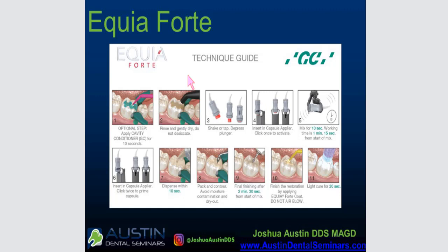And here becomes another issue with this that's not really an issue, but it's just something you have to know, is that this is a dark cure material. This material does not light cure. Equia Forte, you can hold a light on it for 30 seconds. It's not going to do anything. It's got a dark cure. So 2 minutes and 30 seconds is the amount of time you need before you can start finishing this with a burr. Personally, I think 2 minutes and 30 seconds is a lot of time.